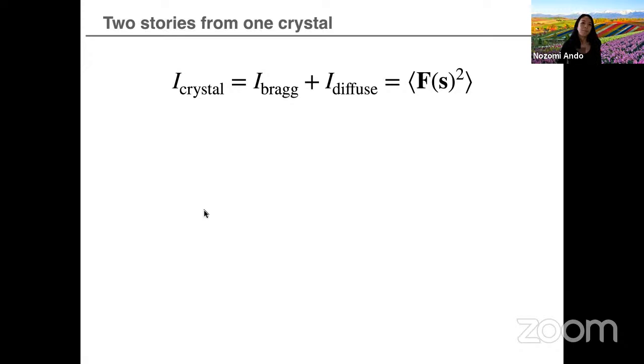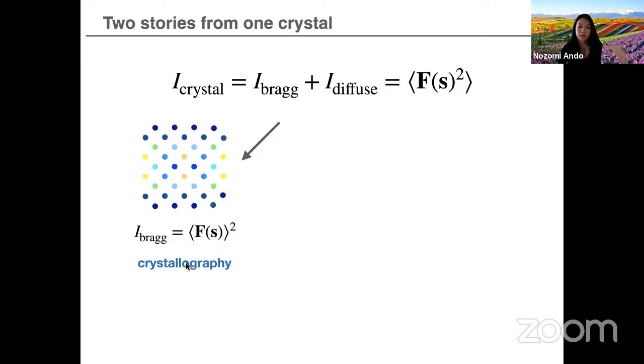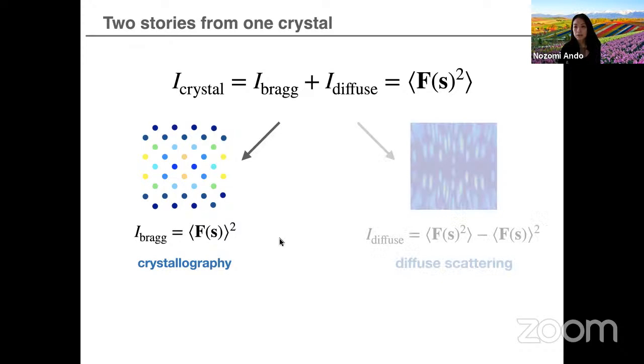The Bragg component is the lattice term, and this is what we use in crystallography. And the main difference between the total scattering and the Bragg diffraction is where the square is. Is it on the outside or on the inside of the brackets? In crystallography, what is actually periodic is the average position. So not surprisingly, we take the average of the structure factor before we take the square. That's the definition of the Bragg diffraction. And if there's any disorder at all in your lattice, then these two are not the same. And so the difference is actually the diffuse scattering signal.